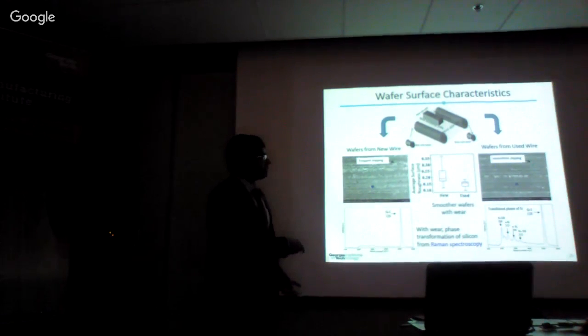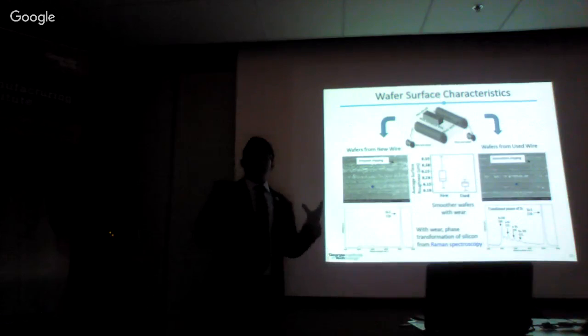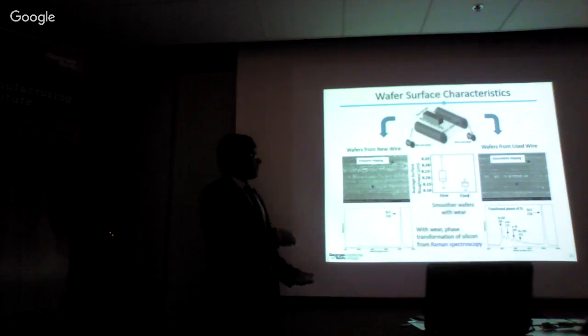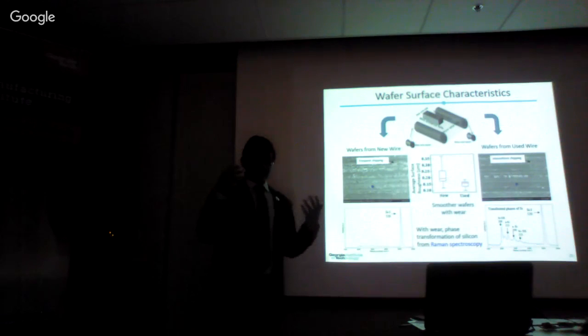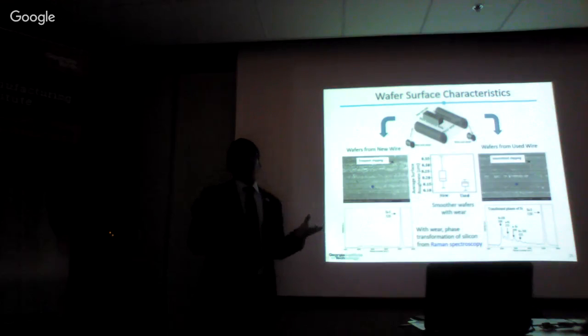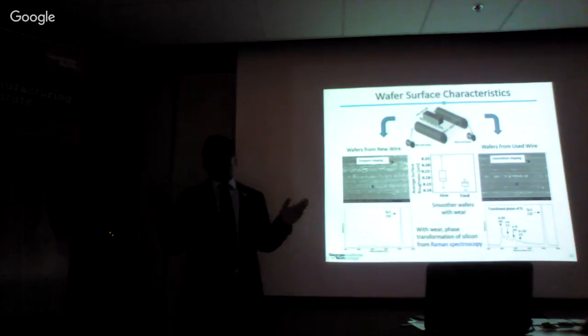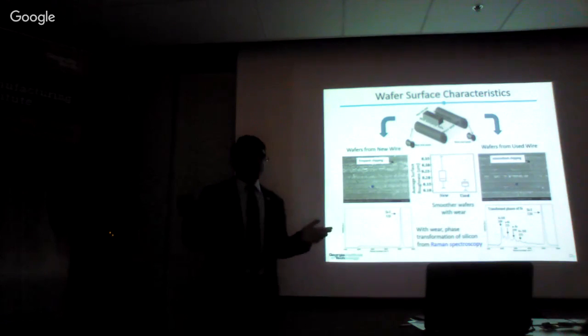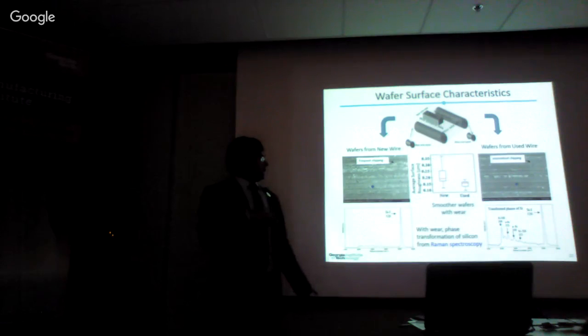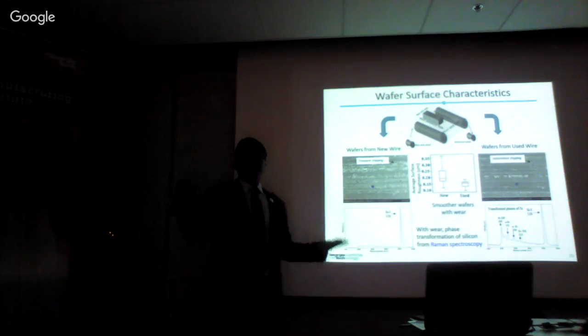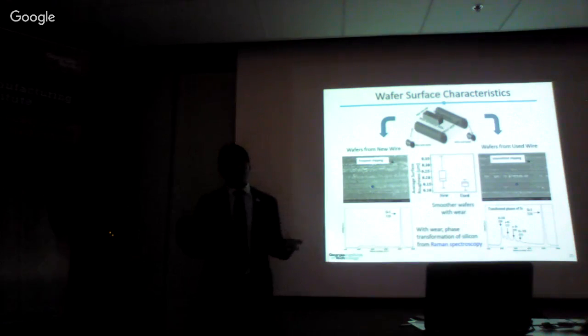Compared to that, the Raman spectra on the wafers from the used wire side, at many different points, and this is just a representative spectrum, we find there is silicon 1, so silicon is in the brittle state, but in addition to that, there is a lot more phase-transformed silicon. Silicon is known to undergo stress-induced phase transformation at a critical stress value of 8 to 12 GPa. This has been found by prior work by other researchers, like Roberts et al. Silicon goes from silicon 1 to the beta-tin metastable phase, which is not found after unloading happens, and then ends up, based on the rate of unloading, as silicon 3, silicon 12, amorphous silicon, and different silicon phases. These silicon phases are more ductile. They are not as brittle.